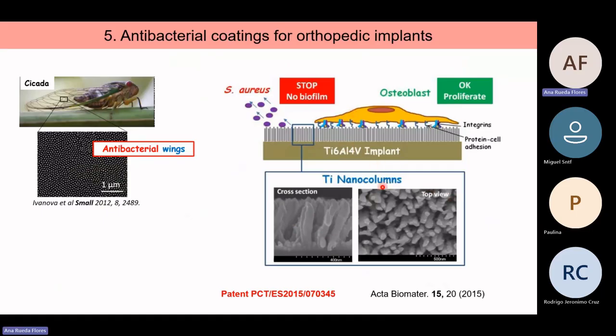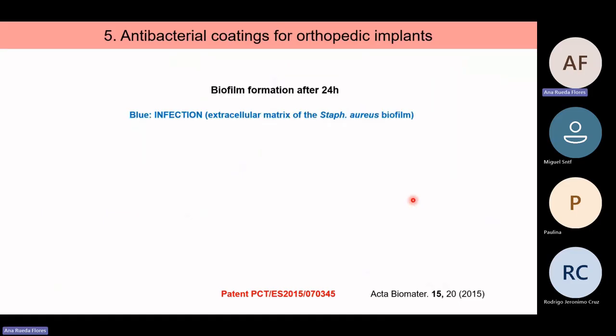So these are the SEM images. This is 500 nanometers. The typical size of a bacterium is around 1 micrometer. So let's say that one bacterium would like to be here, but this bacterium is going to have only a few points to anchor to the surface, the apex of the columns. So it's going to be quite unstable and quite uncomfortable. And that's why we achieve the antibacterial behavior.